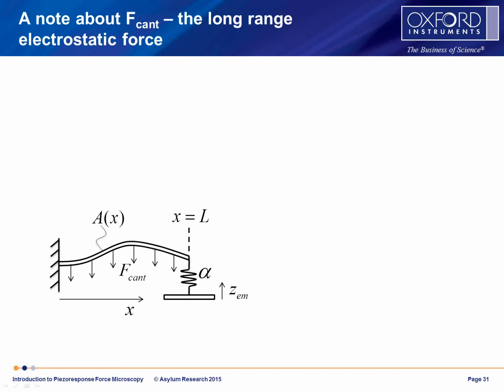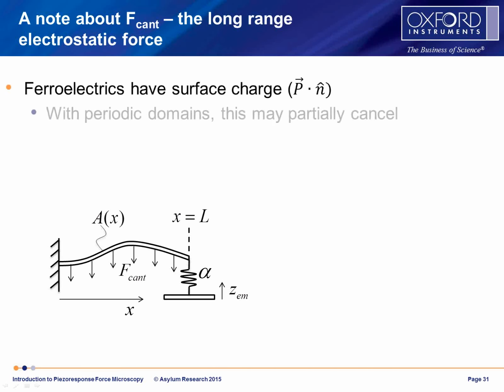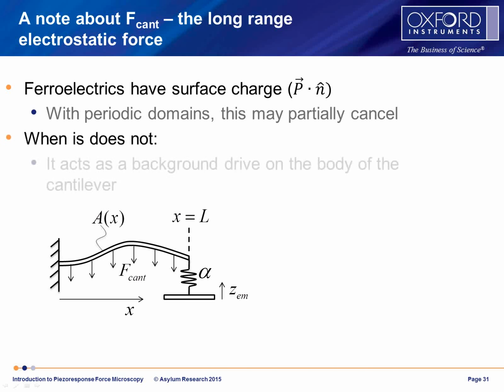I do have to say a quick thing about the long-range electrostatic force in the context of the Euler-Bernoulli model, and that is that most ferroelectrics do have some sort of surface charge. It may be that if there's periodic domains or very small domains, as you get above the sample, that charge more or less sort of cancels. But in many cases it does not, or at least we believe it does not. And when it does not, it is a little bit dangerous in that it acts as a background drive on the body of the cantilever. The force is like charge times an electric field. It's at the same frequency at the first harmonic, which is the same frequency as the piezo response signal. So there's a background in there that you can't necessarily easily get rid of if there is this surface charge.